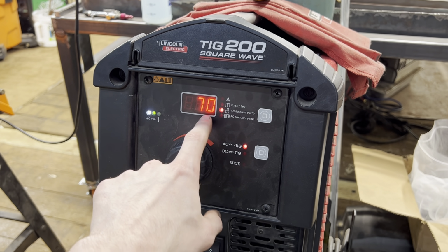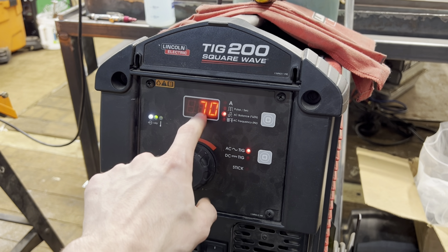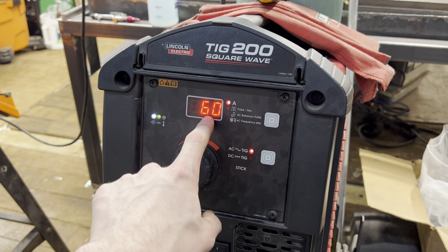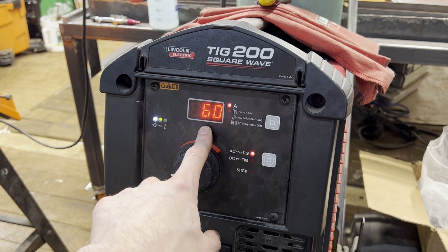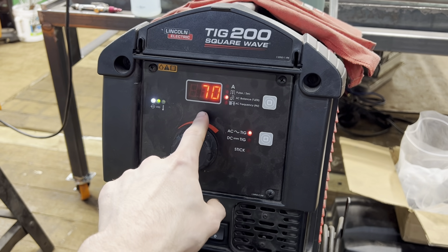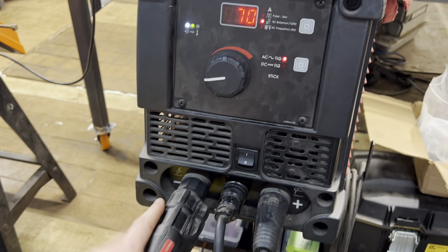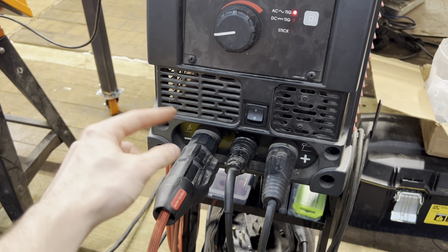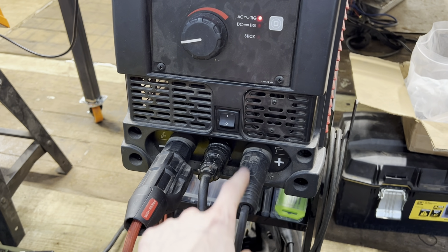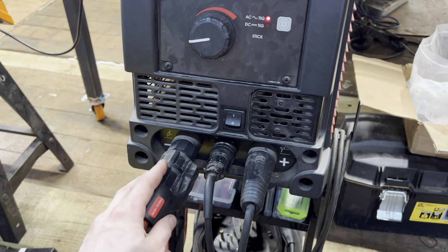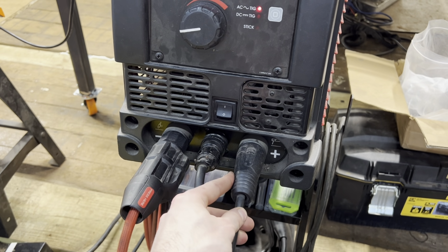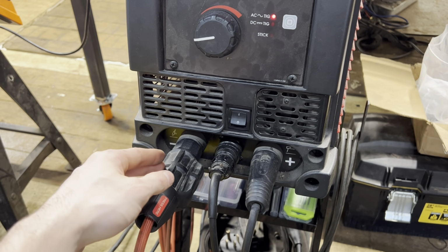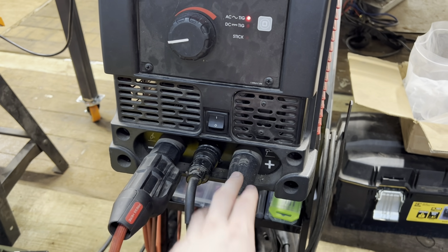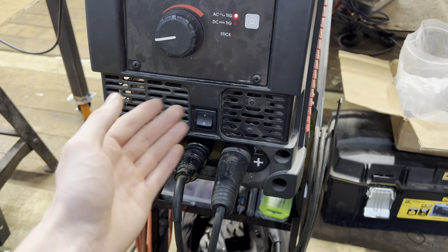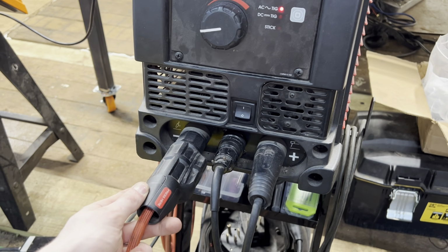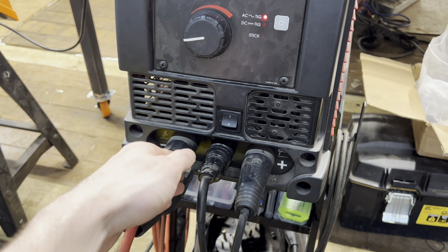One thing to be aware of is that some machines read in electrode negative and some read in electrode positive. You'll want to look that up on your machine before you go into these settings. When I set this machine at 70%, I am setting it for 70% of the current to come from the torch and 30% to come from the ground clamp. What this does is makes 30% come out of the part, 70% go into the part, which gives us 30% cleaning, which removes that oxide layer, and 70% penetration when it's penetrating into the part.